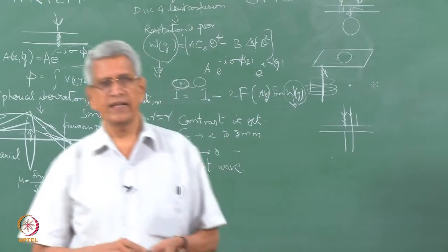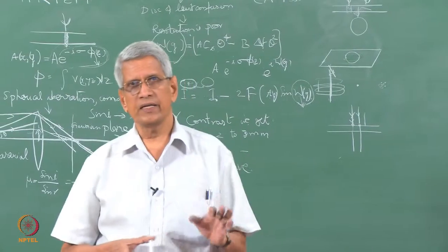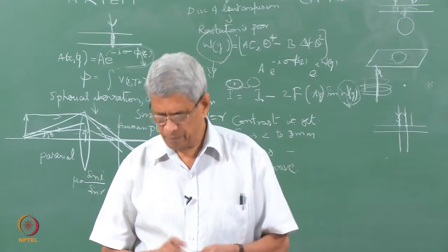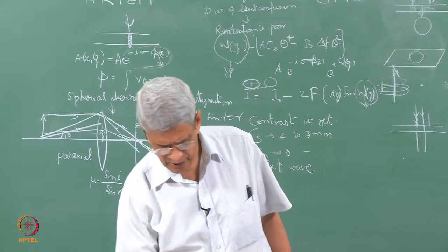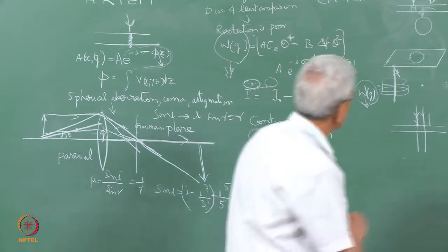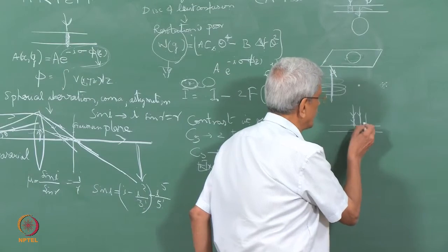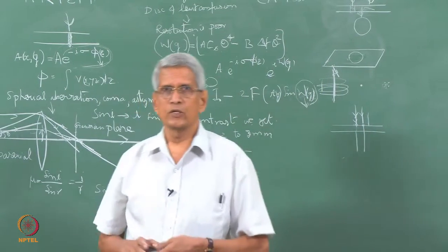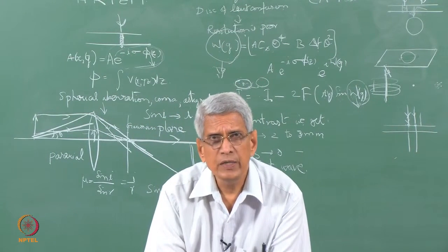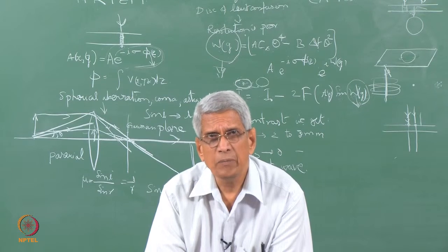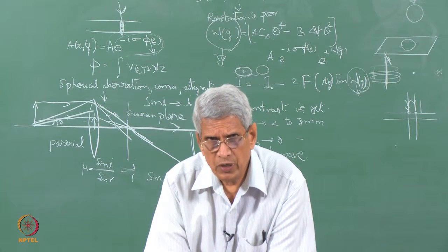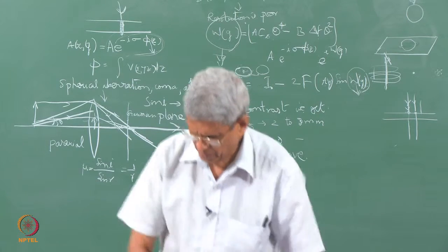If we analyze the diffraction patterns, we can get information about the orientation in the sample from region to region. If there is a variation in the orientation of the sample, that can be detected. This is called orientation imaging microscopy. It is similar to the EBSD image obtained in the reflected mode in a scanning electron microscope.